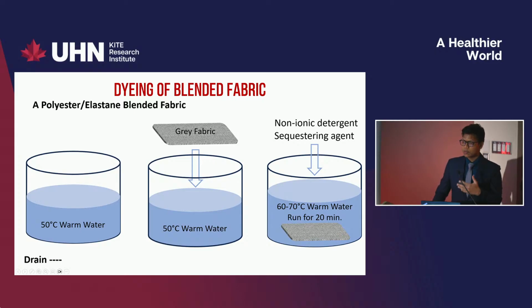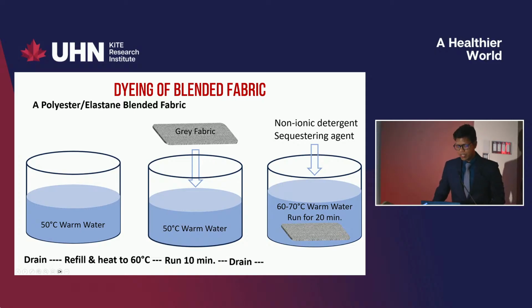And we do this process one more time. After 20 minutes, we drain, refill at 60 degrees centigrade again, run it for 10 minutes, and drain it again. Then we fill fresh water for the next step.